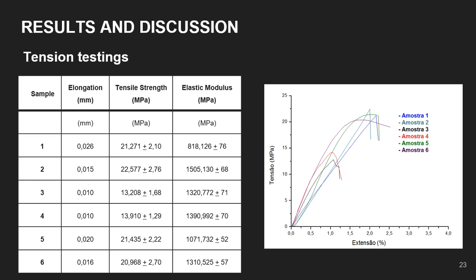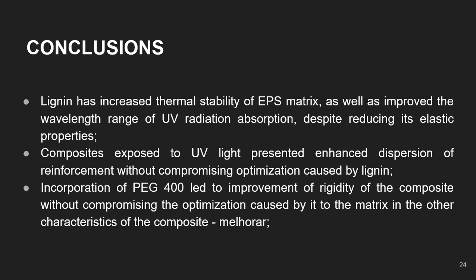With regard to the photochemical treatment, it apparently promotes an increase in the elastic modulus of the materials, which indicates that the 60 minutes of exposure to UV radiation promotes a better distribution of energy through the material when it is subjected to stress. Based on the data presented, it can be seen that the reuse of combined industrial waste